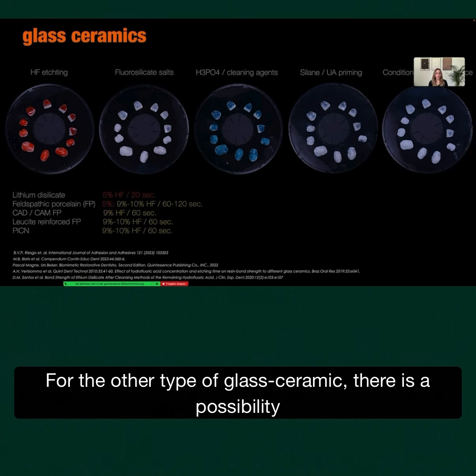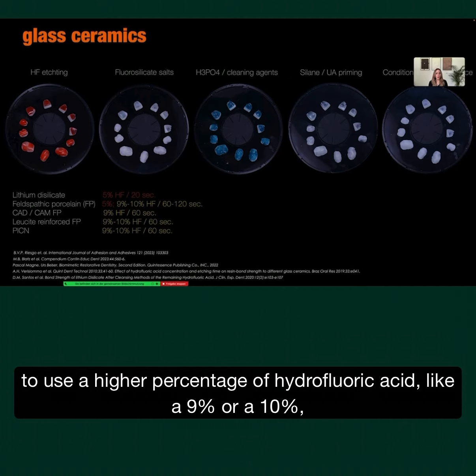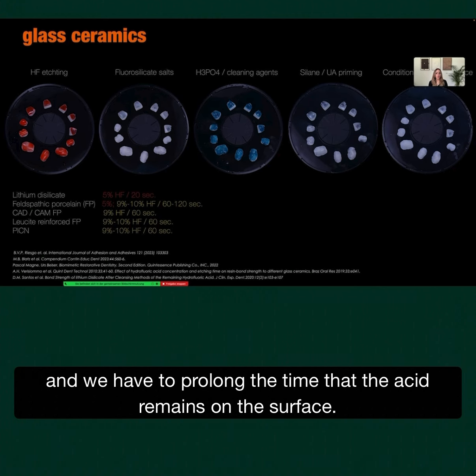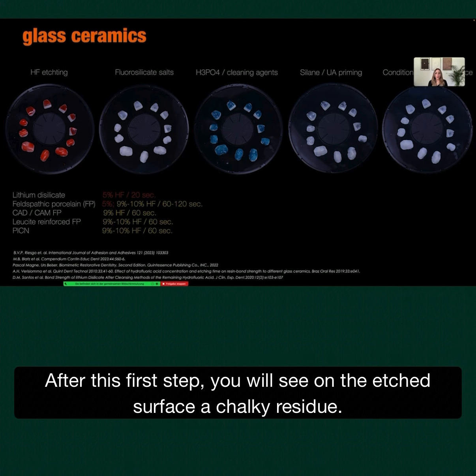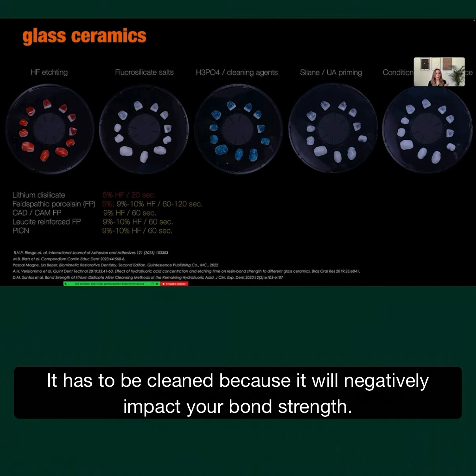For the other type of glass ceramic, there is a possibility to use a higher percentage of hydrofluoric acid, like a 9% or a 10%, and we have to prolong the time that the acid remains on the surface. After this first step, you will see on the etched surface a chalky residue. This has to be cleaned because it will negatively impact your bond strength.